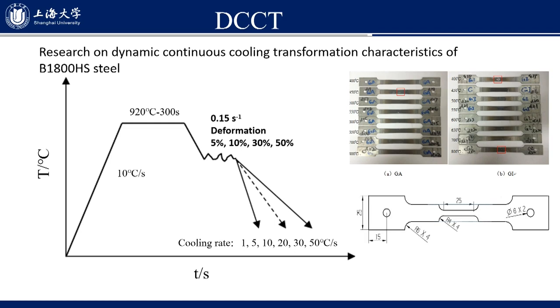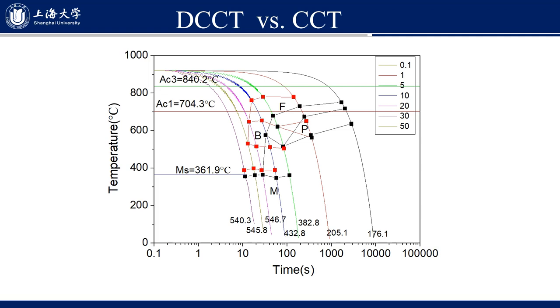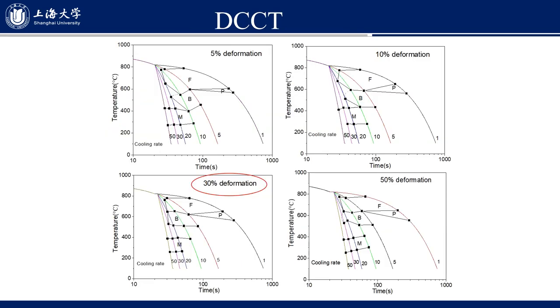Microstructure, microhardness, and mechanical properties were determined by metallographic method, hardness examination, and uniaxial tensile test. Afterwards, tensile test specimens were cut to investigate the microstructure and property of the steel after deformation. This slide shows the dynamic continuous cooling transformation figure of the steel. See the DCCT curves. The red one refers to dynamic continuous cooling transformation, and the black one refers to continuous cooling transformation. This figure shows the dynamic continuous cooling transformation curves of the steel with different deformation amounts, 5%, 10%, 30%, and 50%.